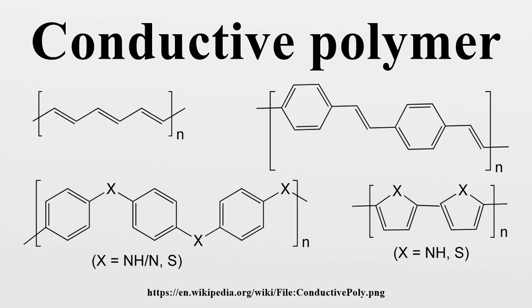In principle, these same materials can be doped by reduction, which adds electrons to an otherwise unfilled band. In practice, most organic conductors are doped oxidatively to give p-type materials. The redox doping of organic conductors is analogous to the doping of silicon semiconductors, whereby a small fraction of silicon atoms are replaced by electron-rich, e.g., phosphorus, or electron-poor, e.g., boron, atoms to create n-type and p-type semiconductors, respectively.